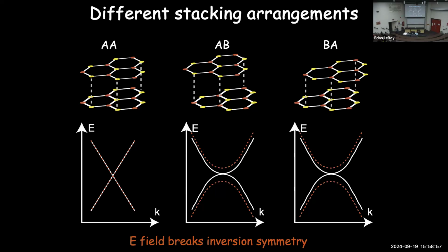So graphene by itself, this monolayer graphene, I already told you it should just be this energy versus momentum relationship, which is just a cone. If you have no twist angle here, well, let me call this AA stacking, so the atoms in one layer are directly above the atoms in the other layer, then it's basically going to be 2 copies of that same band structure on top of each other here. And so you just have that same linear dispersion.